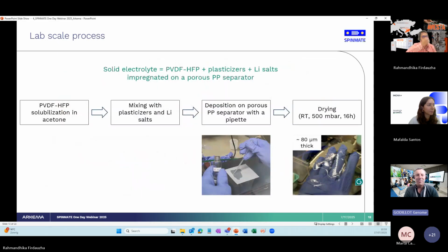No, you can go back, please. This solution is deposited on a porous polypropylene separator with a pipette. So it's a very manual step, as you can see on the picture below. And the last step is the drying. It is dried at room temperature under a small vacuum. And we finally obtain a self-standing film of 80 micron thickness.